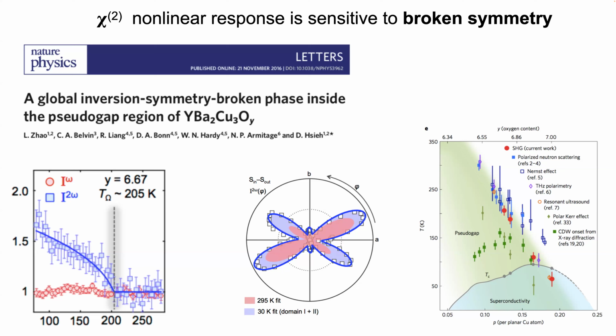And so I think this data here, which was something that I was involved in, the work was done by David Hsieh and his former postdoc, Luyan Zhao, who's now a professor in Michigan, shows that there is an inversion symmetry broken phase in the pseudogap region in YBCO. So there was a distinct temperature scale where the second harmonic signal onset, and this is something which hadn't been seen previously.